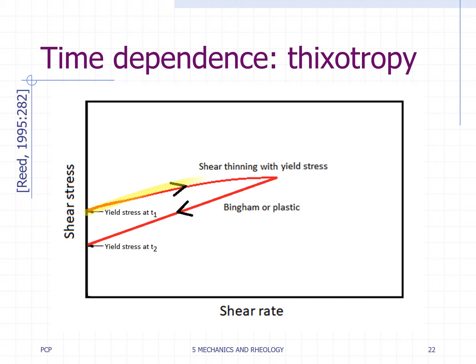Thixotropic behavior in ceramic slurries is often reversible. For a thixotropic material with a yield stress, the apparent yield strength is higher after the suspension has been at rest and a particle structure has reformed. This higher apparent yield stress after a period of rest is often called the gel strength.